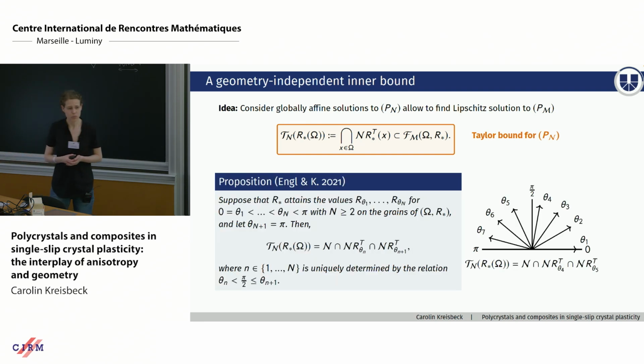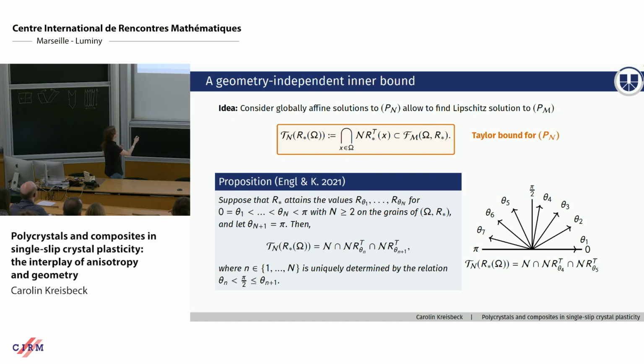Now, usually polycrystals have a large number of grains, so in principle, there are a lot of intersections to calculate here. But the next theorem shows that things are actually pretty simple, that it's enough to only take 3 of them. And here I give you the statement of the theorem. If we have our texture map R star, which takes these values associated to angles in increasing order, we can assume also that the first one is set to 0, no restriction. Under this assumption, we find that the Taylor bound can be determined by just considering the 0 angle and the 2 angles that frame the angle pi over 2. So that's what's here, and I also have an illustration in the picture.